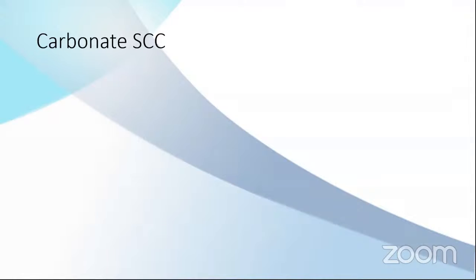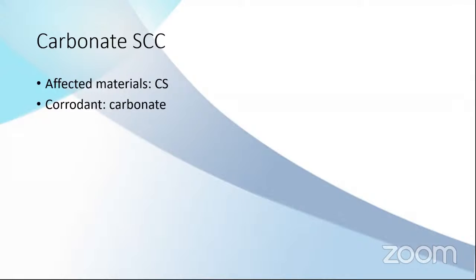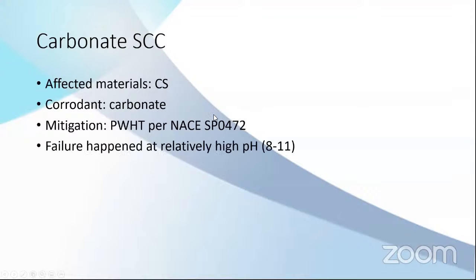Another one is carbonate stress corrosion cracking in carbon steel. The corrodant is carbonate, CO3. For the same mitigation you can refer to the NACE standard. This NACE standard consists of many mitigations for environmental cracking. So not only amine, not only H2S, but many cracking mechanisms in carbon steel. You can read the standard and you can get some information about it. This carbonate cracking also normally happens at a relatively high pH.